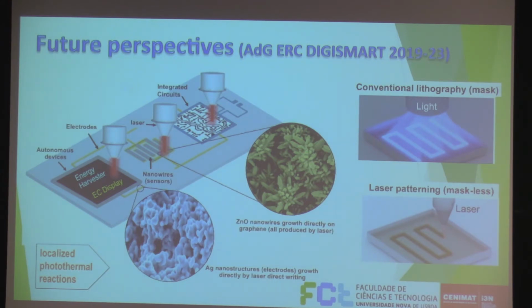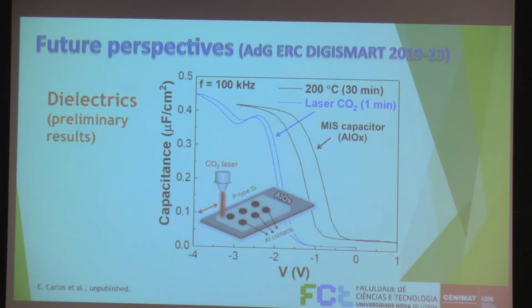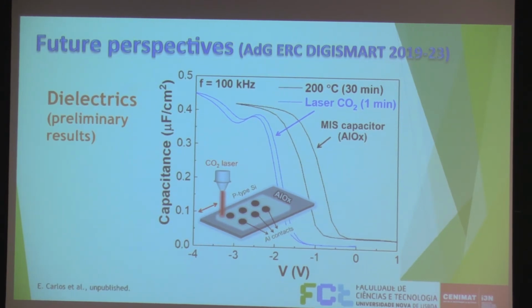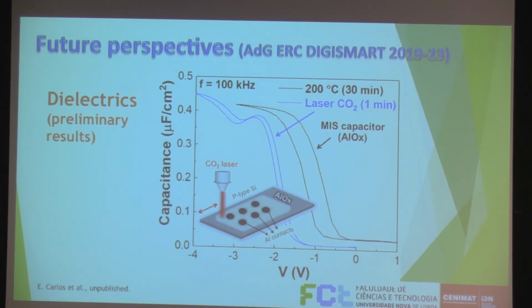So in that case, we don't need to use microelectronic processes because simultaneously we pattern with the laser the areas where we want to promote these chemical reactions. So we want to use this type of technology for different areas: displays, sensors, batteries, and so on. Here's just an example of some preliminary results where we use a spinner, we spin the precursor for aluminum oxide, and by using a CO2 laser, we promote the chemical reaction, and we achieve very nice results.